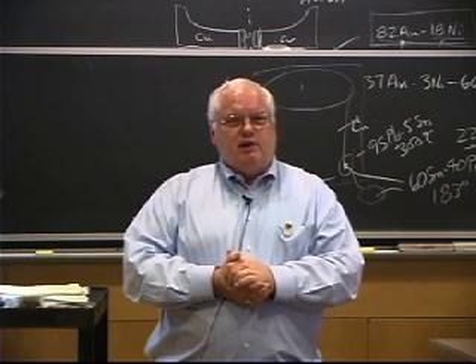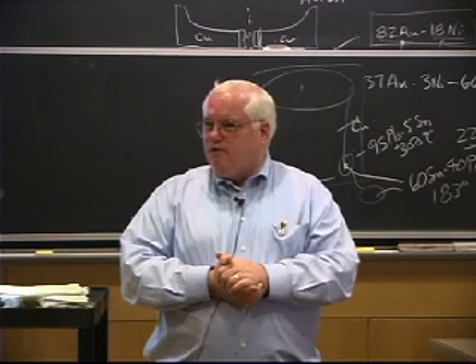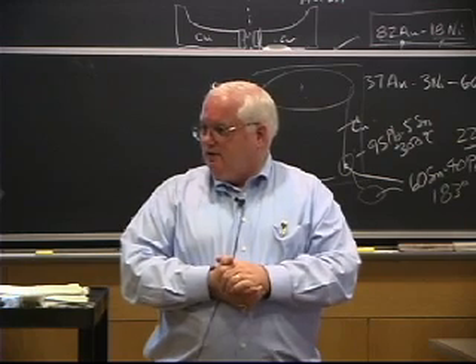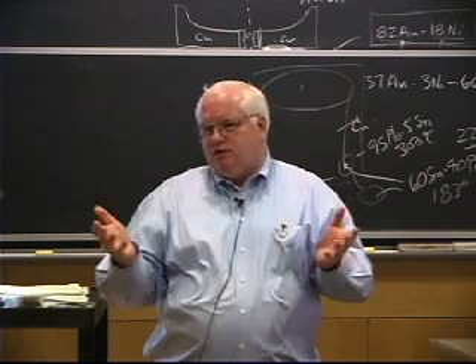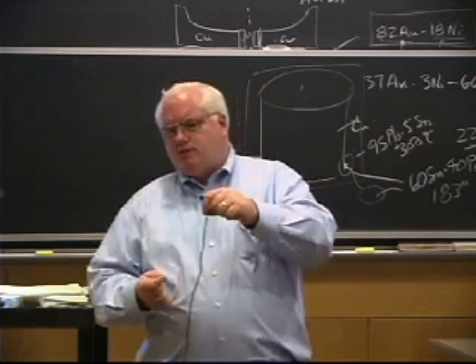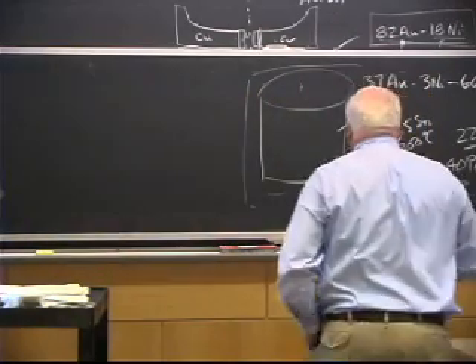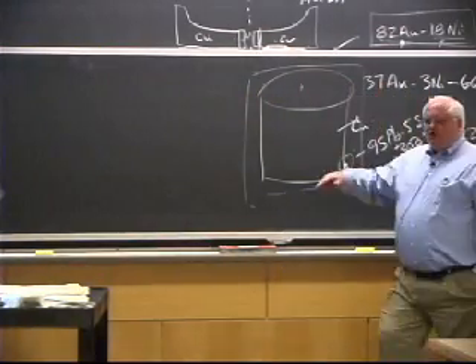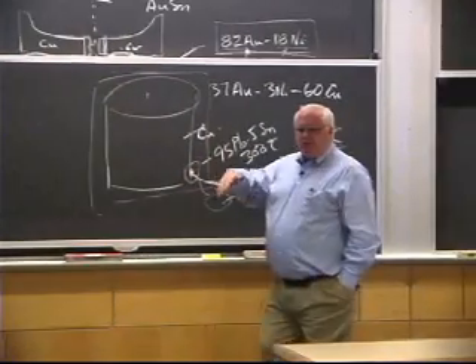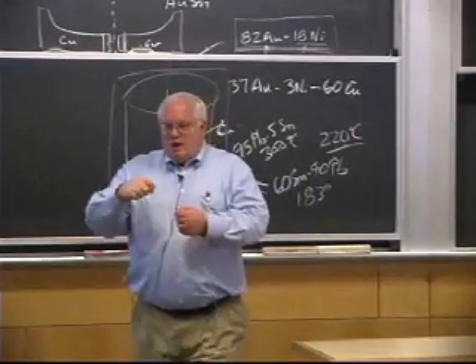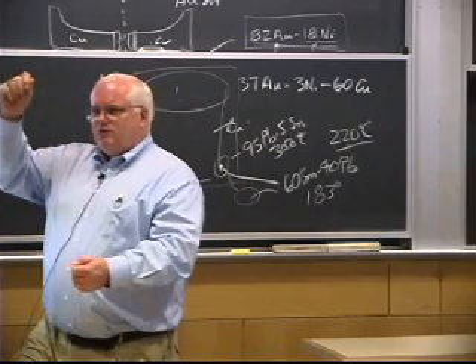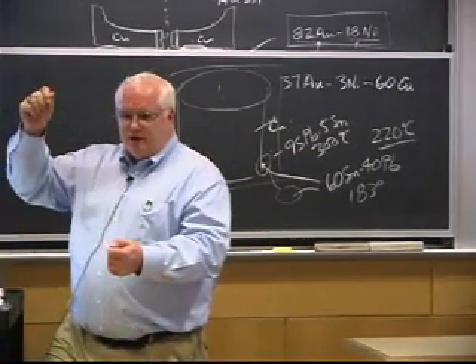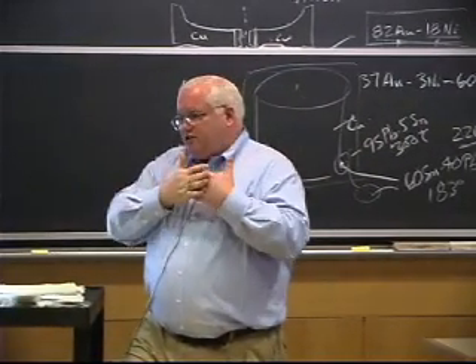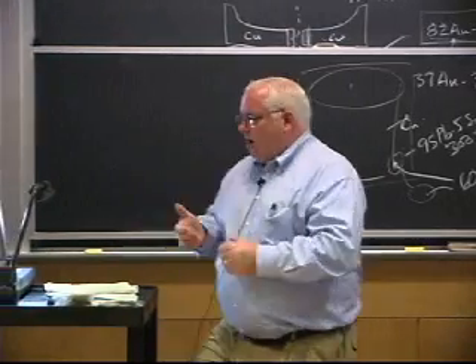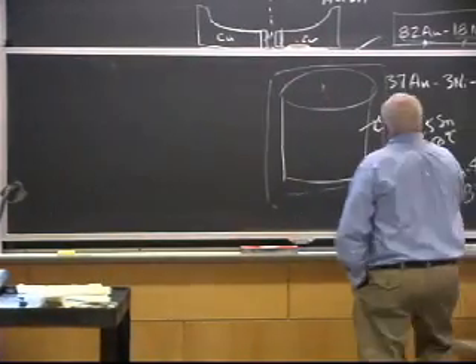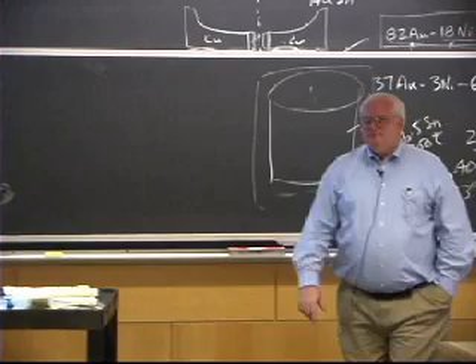They explained all this to me, and I said, "Oh, you don't have a problem. All you've got is a TLP joint." And they said, "What do you mean? What's that?" So I explained what TLP was. And they said, "Well, we've done some tests. We actually took some afterwards, and we soldered them with the eutectic lead tin, and we stuck them in a furnace at 220. These were just test specimens, just copper sheets with wires on them. And then we did tensile tests, and we found they didn't fall apart until 300 degrees centigrade." I said, "Well, that's right, because the tin just diffused into the copper and left behind a rich lead inner layer right here." Okay?